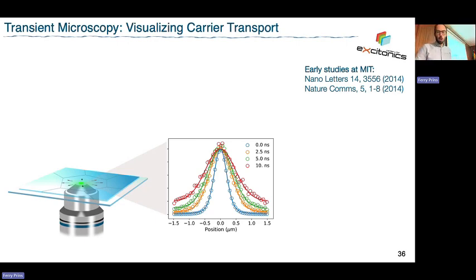Okay, this is all qualitative, but you can quantify this. Take the variance of that maximum of your population at this point in time, and we're going to compare the population at time t with the original one. Square it, and what you get is what we call a mean square displacement, or in this case, actually a mean square expansion of your population. How fast does it expand?